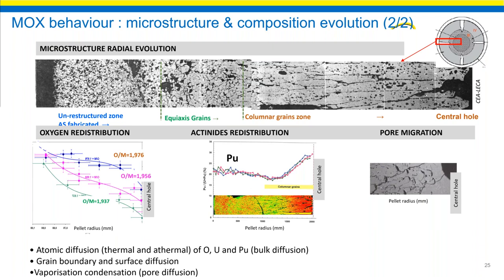Regarding compositions, the figure on the left side illustrates the evolution of O over M. The stoichiometry decreases around the central hole and increases on the periphery of the pellet. The oxygen migrates down the thermal gradient. At the end of the fabrication, the fuel is slightly under-stoichiometric, around 1.97. And this oxygen redistribution is very fast because its diffusion velocity is very high. The oxygen migration is due to solid phase transport and gaseous transport also.